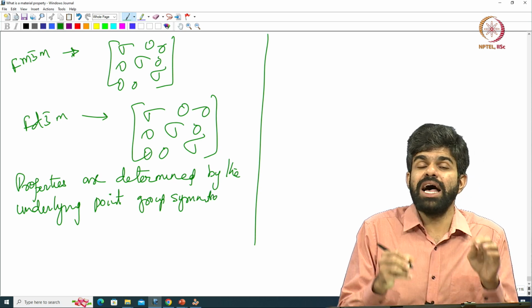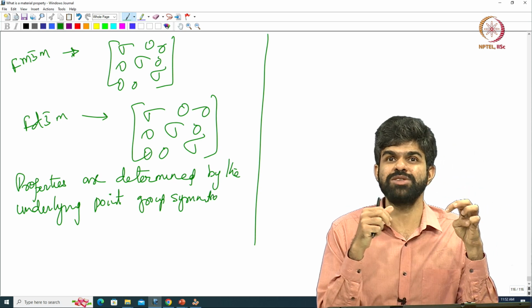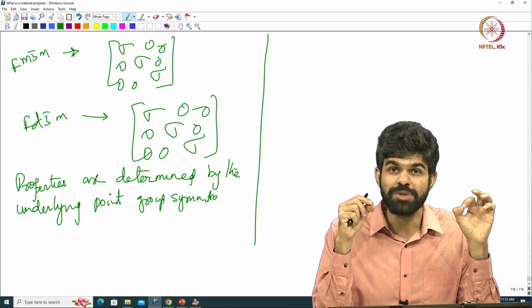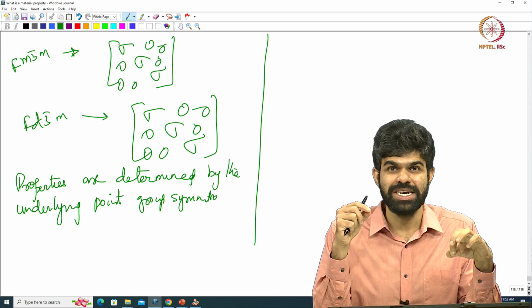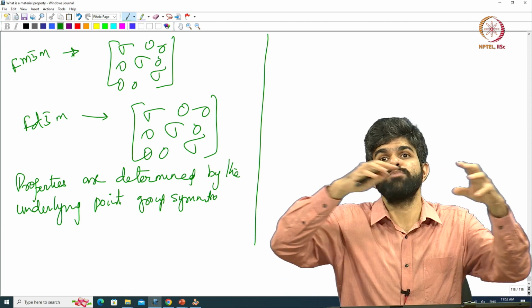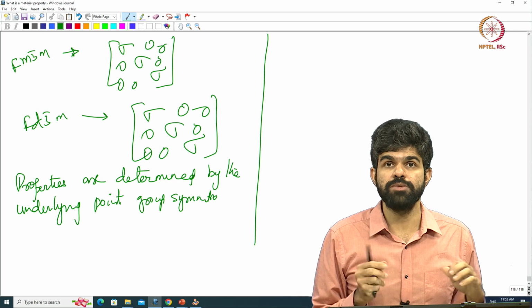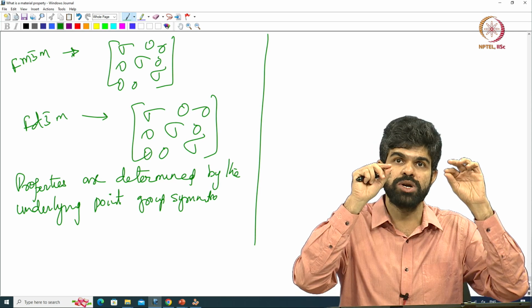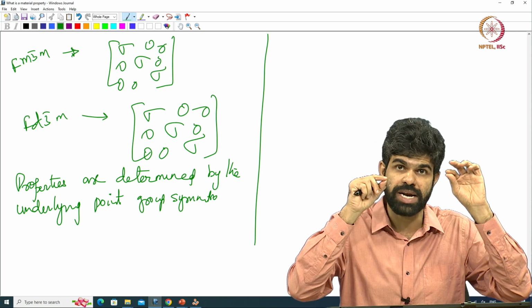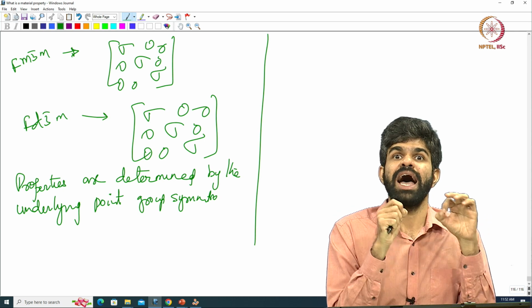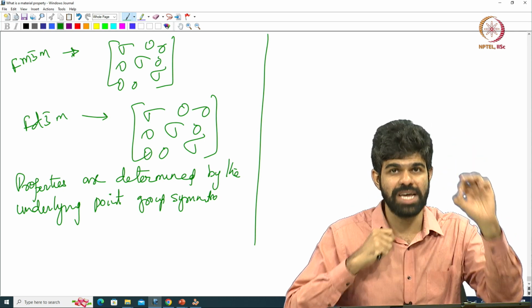So, in all these non-symmorphic space groups, there does not need to be a point with that symmetry, but still all the other points, all the glide operations and screw operations conspire to give you that higher symmetry point group, and the crystal behaves as if it has that point group.